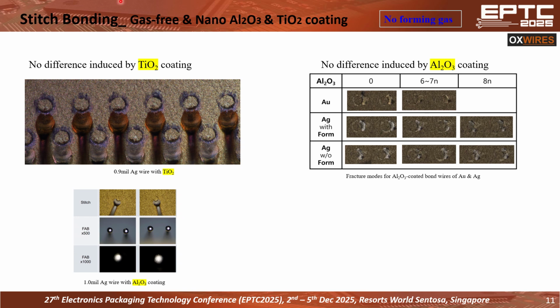We have to look at the stitch bonding pattern. Our nano ceramic coating did not result in any difference in terms of a stitch bonding shape. On your right hand side, zero means zero coating, and the other is an 8 nanometer thick Al2O3 coating. When you look at the fracture mode at the stitch bonding, they are almost identical, indicating that the stitch pull strength is not going to change by introduction of the Al2O3 passivation coating. And I'm going to show you the data on the next slide. I have to emphasize again, no forming gas was used. And the wire was silver wire 1.0 mil, 0.9 mil silver wires, and the passivation type was TiO2 and Al2O3 passivation.